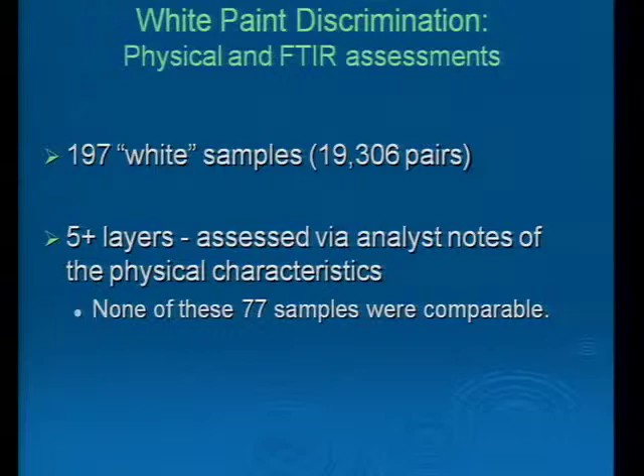We decided the best thing to do was, having gone through and assessed all of these samples as having a white top coat layer, to go back to the paperwork we as analysts had originally used to characterize the underlying layer structure. Anything that had five or more layers was pulled from the population and assessed just based on that visual microscopic assessment initially. There were a couple with less than five layers but very unusual layer structures — a white, a forest green, a white, or a white, a bright red and a white — all of those, constituting 77 samples, were not comparable by intercomparison of that visual microscopic assessment.